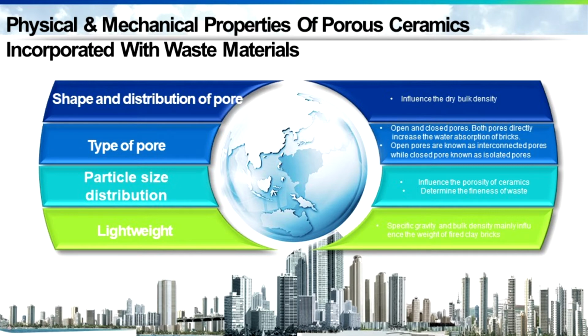Second, types of pores. There are two types of pores, which are open and closed pores. Both pores directly increase the water absorption of porous ceramic. However, open pores, also known as interconnected pores, are responsible for lowering the compressive strength. Meanwhile, closed pores, also known as isolated pores, can increase the compressive strength.